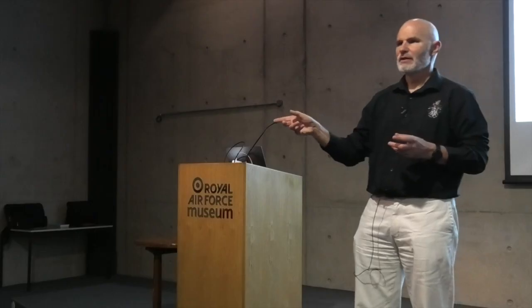Hall-Petch says if you want increased strength, so tensile strength, you go to finer grains. If you want high creep resistance, you go to bigger grains. So depending on whether we want tensile strength or creep strength, because they're two different mechanisms, we have to pick our structure. And actually, it's creep strength that dominates in this application, hence we go for single crystal. In other parts of the engine, it's tensile strength, so we go for fine grains. But for the turbine blading, it's creep.